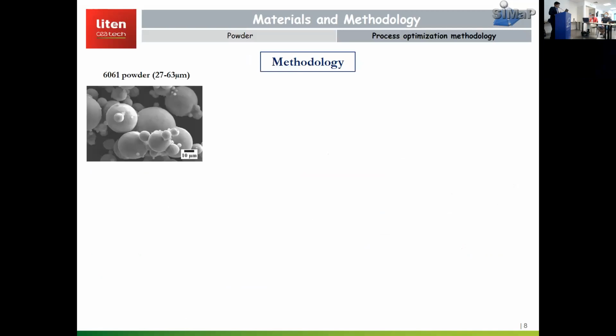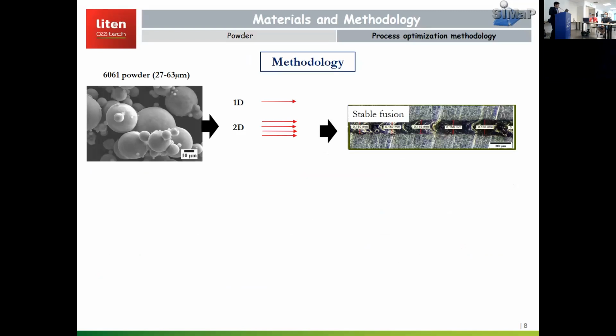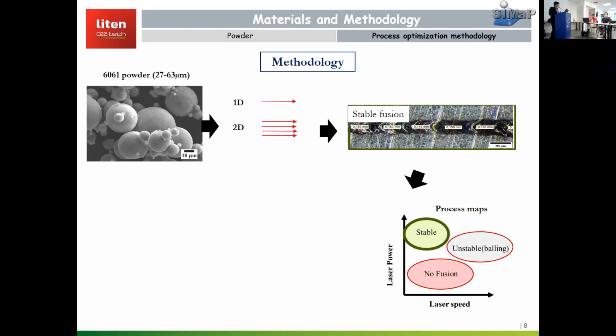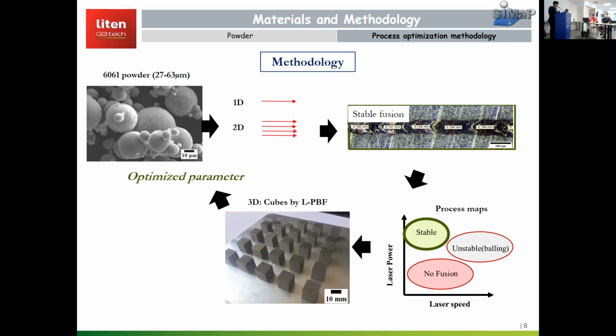Now the methodology of the work. We started with the powder. We did some 1D analysis, 2D track analysis with the laser tracks. So the goal was to just identify stable melting conditions. And based on the stable melting conditions, we can identify the process parameters, for example, which laser power and which laser speeds are needed to attain the stable melting conditions. And once we have that, we can print 3D cubes and finally identify the best optimized parameter.